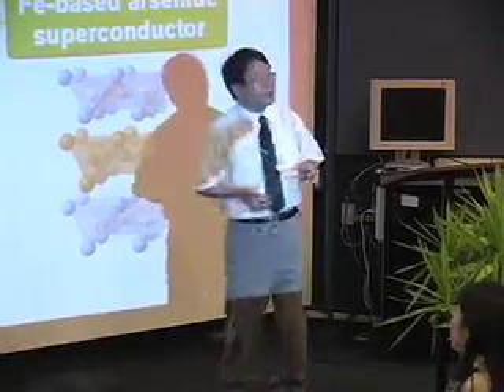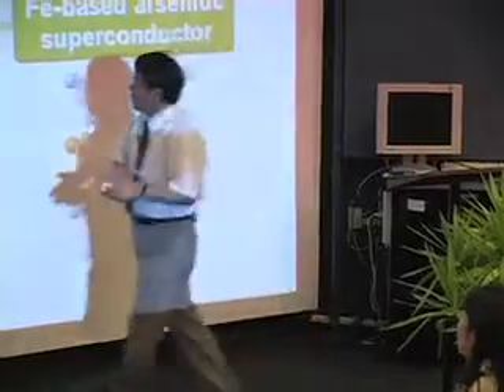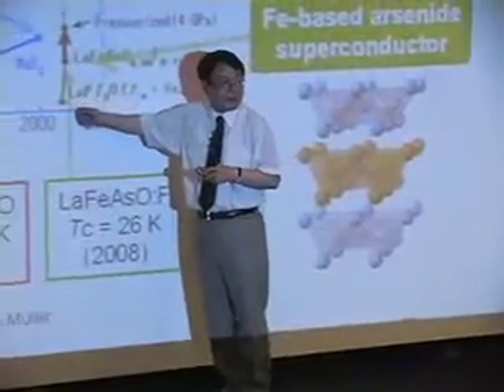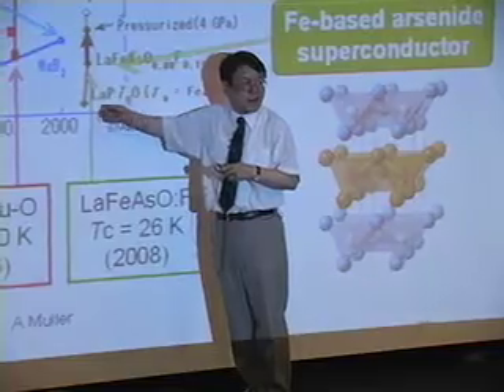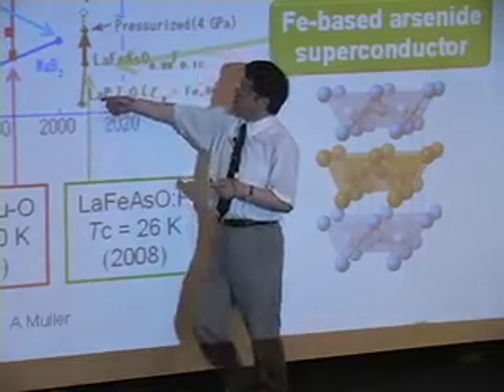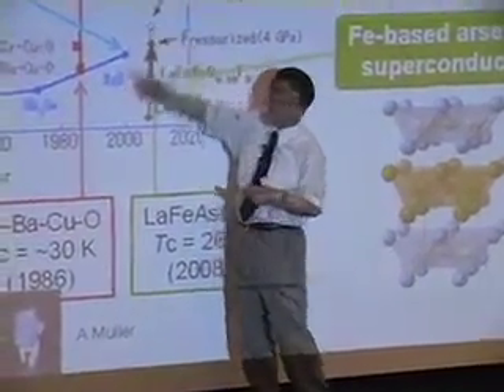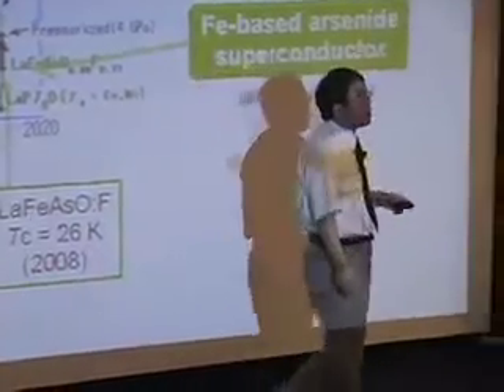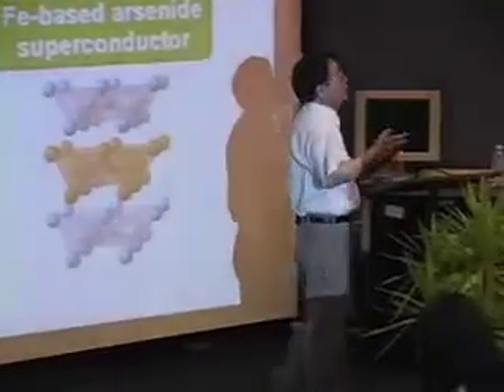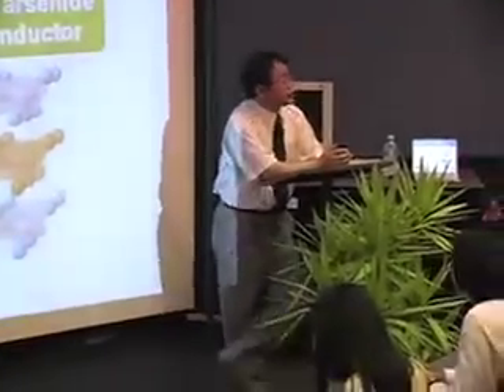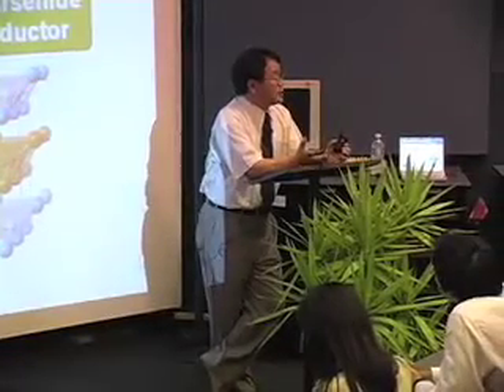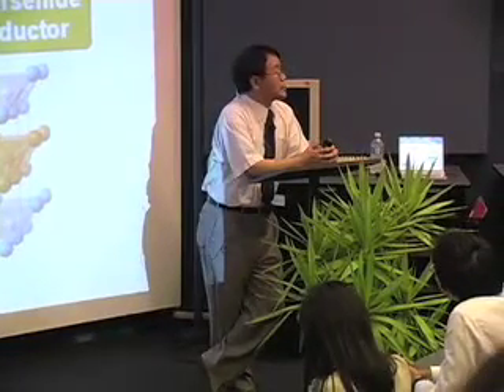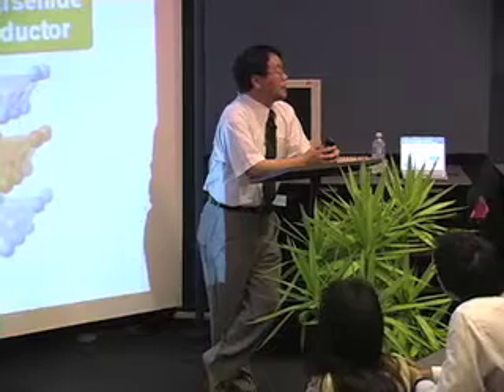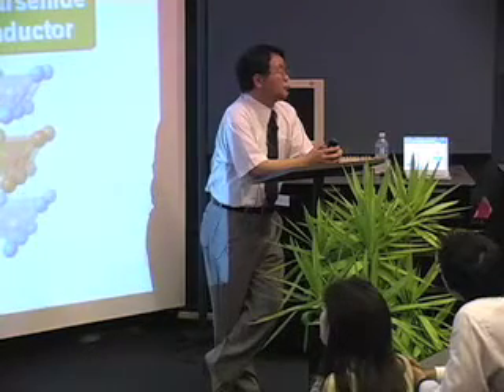But to our surprise, almost by chance, we discovered iron-based superconductors in 2006. After that, Tc dramatically increased, and now the maximum Tc is 57 K. As introduced in his talk, more than 1,000 papers have been published to date.